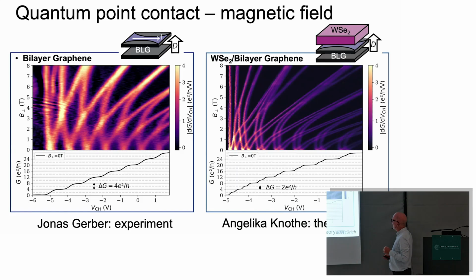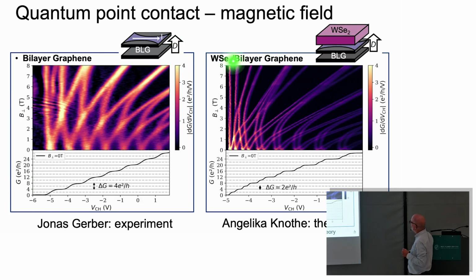Now you do the same thing on bilayer graphene with tungsten diselenide. You see each of those states has split into two, and those two states move parallel in magnetic field. The scale I told you is a gate voltage. The gate voltage can be converted to energy, so that's an energy scale. So you can already read off the distance from here to there. That's the energy scale between the ground state of the confined system and the first excited state. Similarly, on the right-hand side, the energy separation between here and here is simply the spin-orbit interaction.